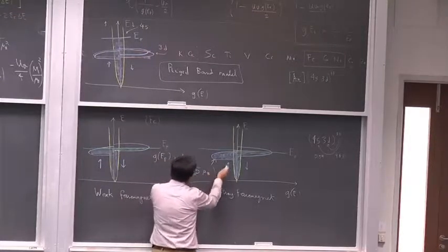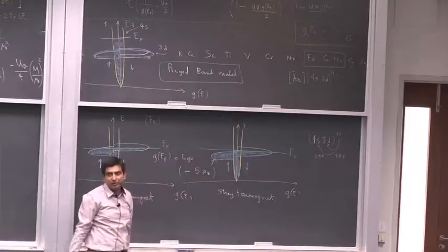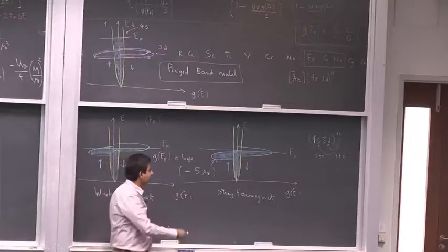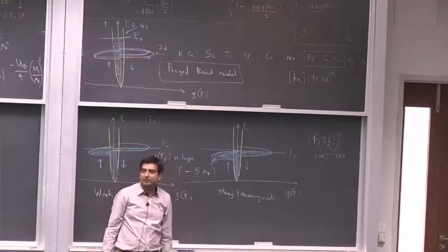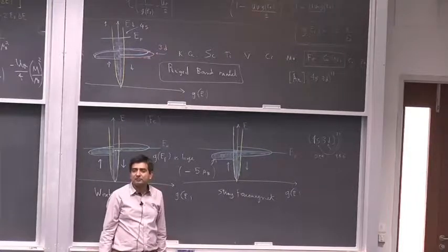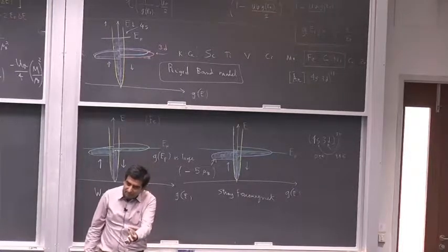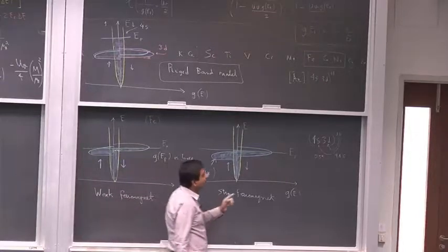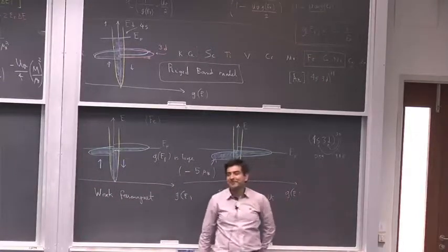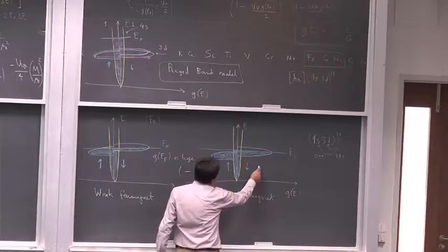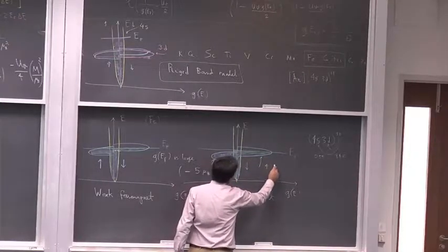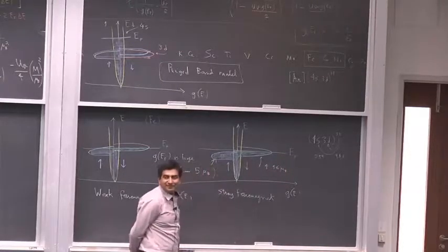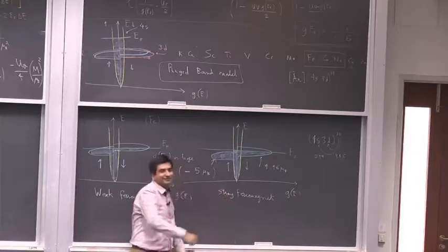This is the magnetization due to this spin sum, minus 5 mu b. Plus or minus, I'll just call it minus 5 mu b. Each electron has a magnetic moment mu b, so 5 of them will have 5 times mu b. So you are left with 4.46 electrons. Those 4.46 electrons have to go here. So you have 4.46 mu b here of the other kind.